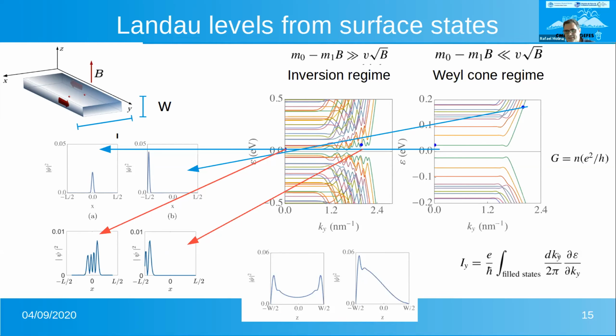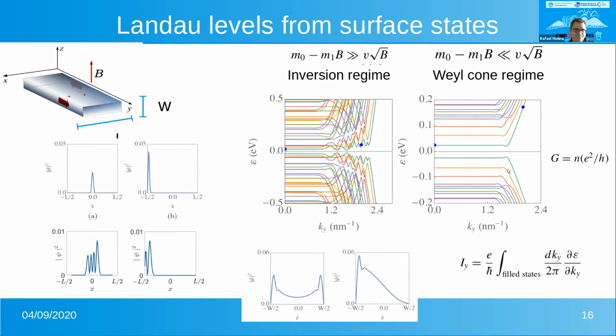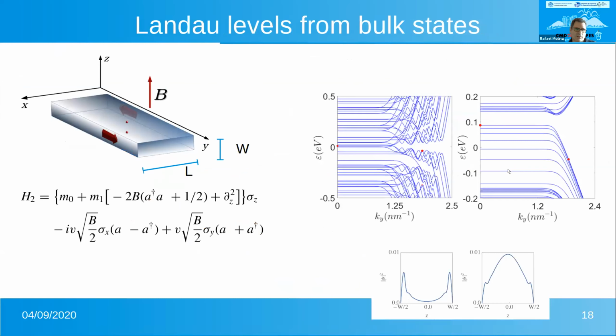So if we want to find the Hall conductance here, you will have contributions to the current that really you cannot expect to find quantized conductance, because you will have contributions up, down, with different signs, a very complex situation. While in the Weyl cone regime, you will have a very nice quantized conductance due to this nice behavior. In the other geometry, you have a very similar situation, although the states now live mostly in the bulk.